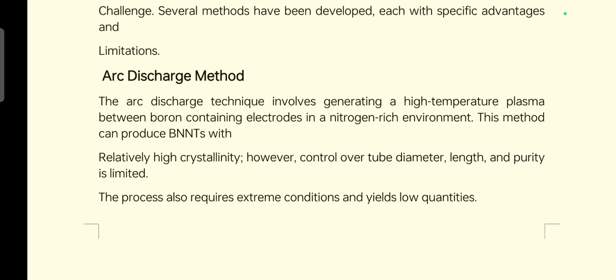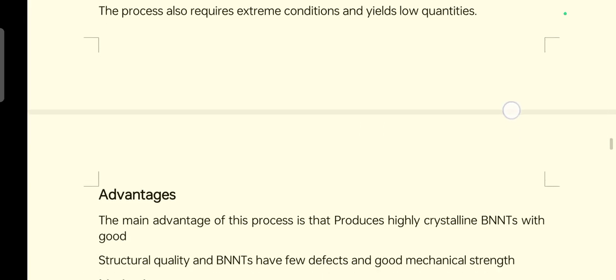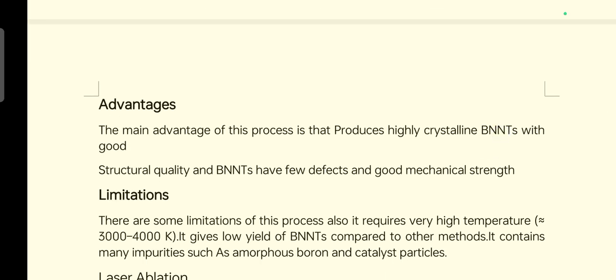The arc discharge technique involves generating a high temperature plasma between boron containing electrodes in a nitrogen rich environment. This method can produce boron nitride nanotubes with relatively high crystallinity. However, control over tube diameter, length, and purity is limited. This process also requires extreme conditions and yields low quantities. Here we will discuss the advantages. The main advantage of this process is that it produces highly crystalline boron nitride nanotubes with good structural quality, and they have few defects and good mechanical strength.